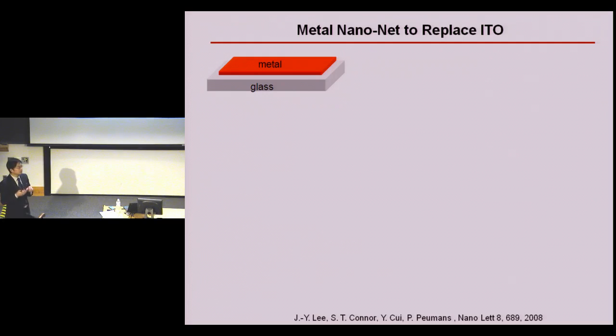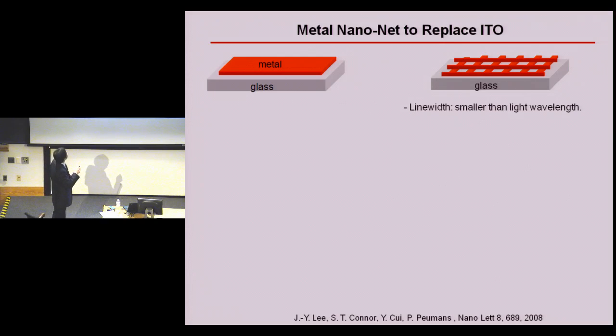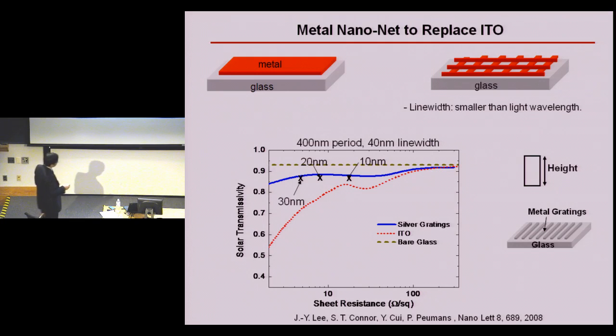But meanwhile, the sheet resistance will increase dramatically because of the scattering of the electrons due to the roughness of the glass substrate. So how about we cut some material from some spaces and put it on top of the other areas, so we have this kind of metal grid structure. Professor Peter Peumans at Stanford University did some simulation on this kind of metal-based structure. You can see from the simulation, we can get 90% transparency and 10 ohm per square sheet resistance, which is perfect for solar cell application.